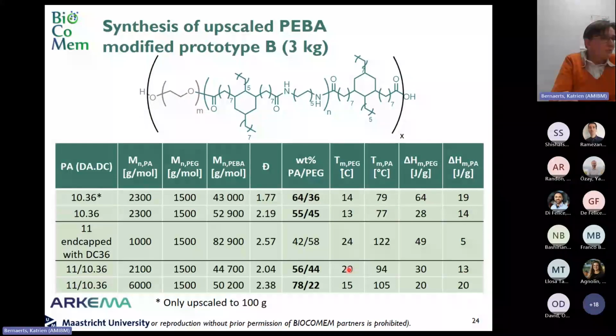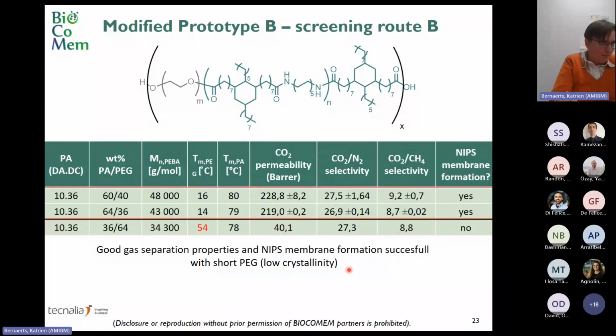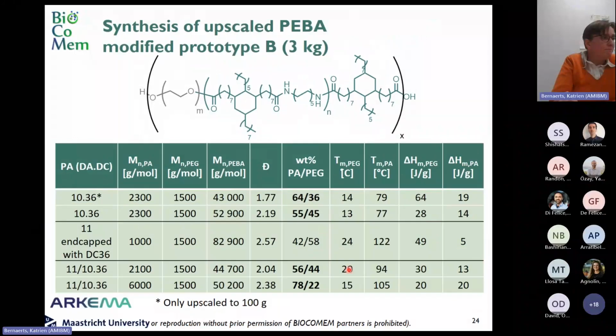So after those lab scale experiments and screening experiments were done, we went to upscaling and we went from tens of grams of polymer to 3 kilograms of polymer, and this is mainly done with Arkema. So we selected those polymers that gave good membrane formation and good gas separation properties, as well as processability. And also some variations of those polymers were made. So in the first two lines, you see we varied the amount of PEG, so 36% or 45% of PEG.